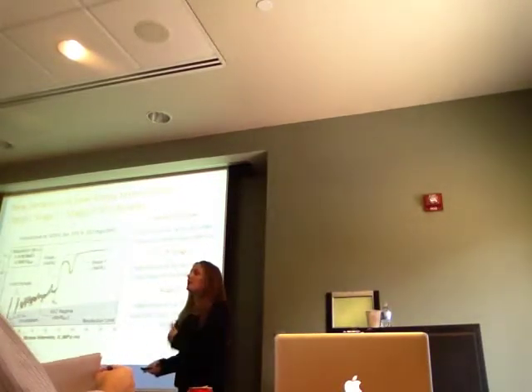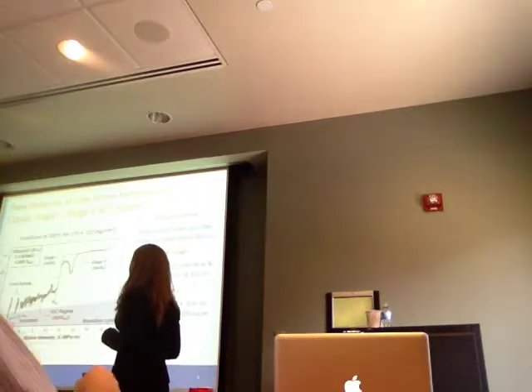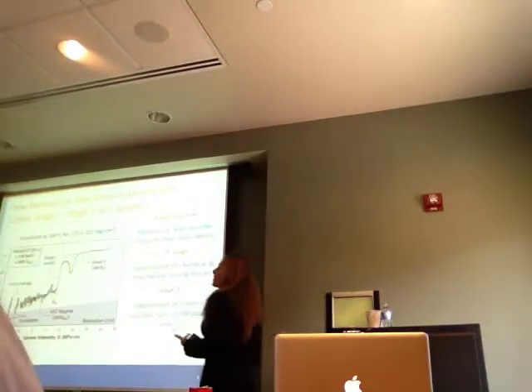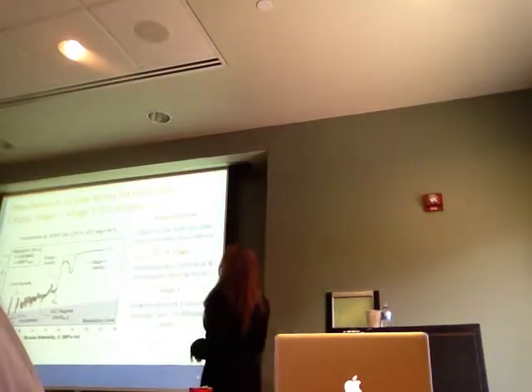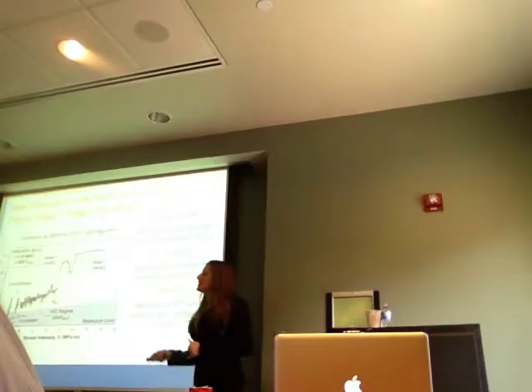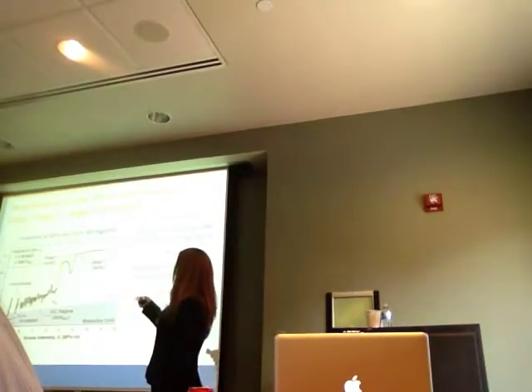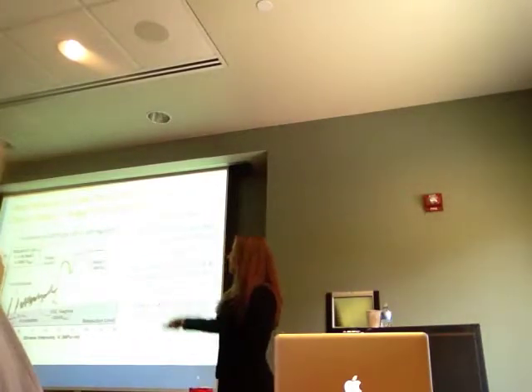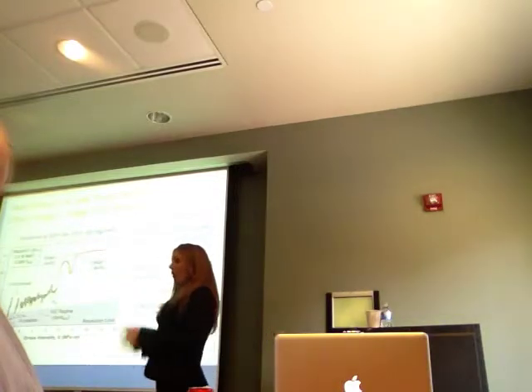So once you get to your threshold stress intensity, you meet stage 1 stress corrosion cracking. This stage 1 and stage 2 is typical of all stress corrosion cracking. Stage 2 is usually due to your hydrogen diffusion limited crack growth rate. So we can use a stress intensity, I particularly use 15 MPa root meter for this data set, and the threshold stress intensity to quantify all stress corrosion cracking in this alloy.